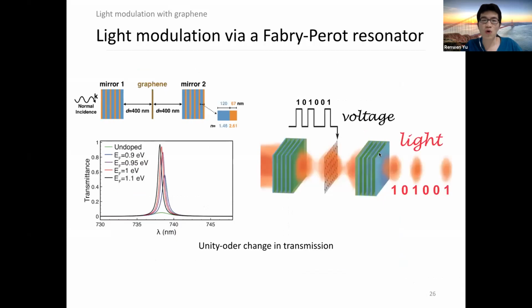To do so, we can integrate or embed a graphene layer in the center of a Fabry-Perot cavity defined by two Bragg mirrors. By careful design, we can have a maximum field enhancement at the center of the cavity. After boosting the field enhancement at the graphene plane, we can boost the light absorption of graphene, as shown here. When we change the doping level of graphene from its undoped state gradually to a highly doped state, we can have a unity-order change in transmission, basically from 100% to close to 0% at wavelengths around 740 nanometers.